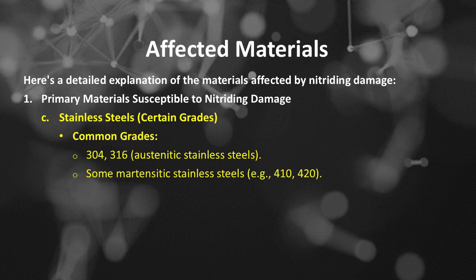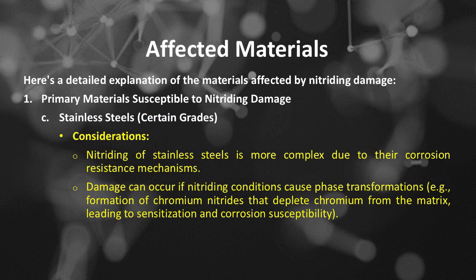Another primary material susceptible to nitriding damage is stainless steels. Common grades include 304, 316 or austenitic stainless steels, and some martensitic stainless steels such as 410, 420. Considerations: nitriding of stainless steels is more complex due to their corrosion resistance mechanisms. Damage can occur if nitriding conditions cause phase transformations such as formation of chromium nitrides that deplete chromium from the matrix, leading to sensitization and corrosion susceptibility.